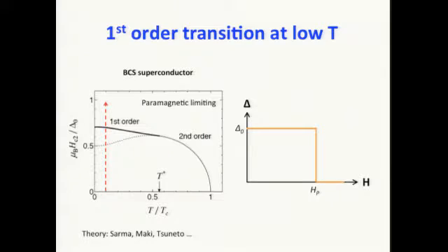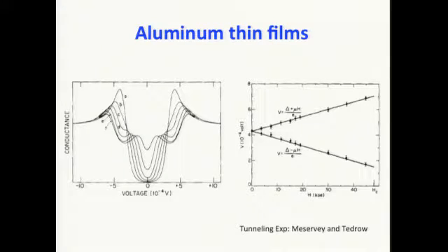So if you can measure the order parameter as a function of magnetic field at low temperature, you can tell whether it's a first order or second order phase transition. This actually has been done not far from here by Meservey and Tedrow for a few nanometer thin aluminum film, which is a BCS superconductor. On the left-hand side, I show the tunneling spectrum for this material. You can see that with increasing magnetic field, the tunneling spectrum turns from one single peak into a double peak feature because of Zeeman splitting. I also want to point out that even under very high magnetic field close to the critical field, the order parameter, defined by the superconducting gap from here to here, is almost unchanged. Only when you go beyond this does the gap suddenly close, so the material turns normal.